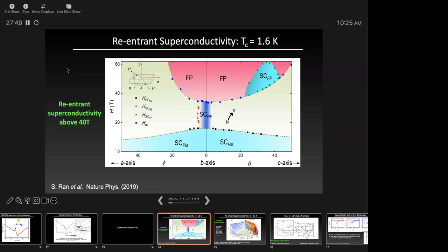So that's the first thing. And the second thing is, in a different direction, if you apply a magnetic field in this direction, so this angle is from the B to the C axis, this is the B axis, somewhere in this direction you kill superconductivity, and then it stays killed. And then at some high magnetic field, you get another superconducting phase. So it's very strange, and typically this kind of phenomenon where you get reentrant superconductivity with magnetic field is seen in triplet superconductors. So this is why I bring this up. This is the first indication that this actually might be a triplet superconductor.